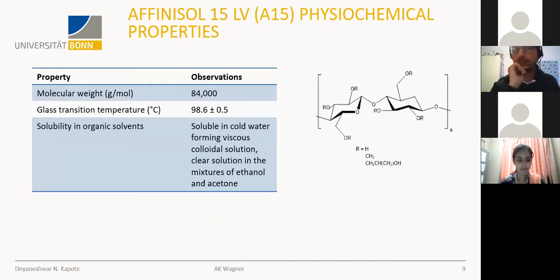Then the next polymer I investigated was Affinisol, which was launched by DuPont in 2015. It is an HPMC based polymer with a very low glass transition temperature. Conventional HPMCs have a glass transition temperature above 150 degrees Celsius, making processing a challenge for hot melt extrusion. DuPont came up with a polymer having a glass transition temperature of 98.6 degrees Celsius. So we can extrude it below 150 degrees Celsius, which is very good for an API that degrades at higher temperature.